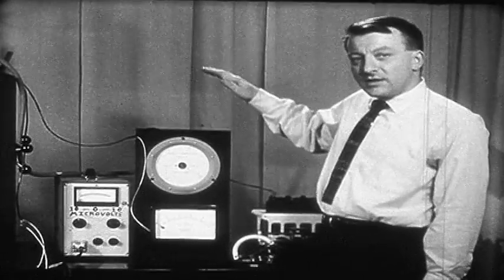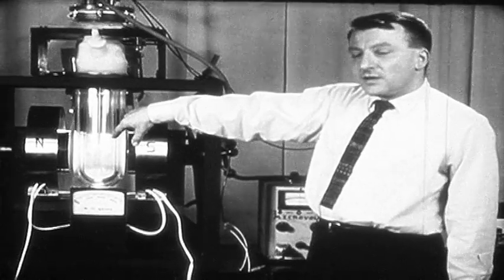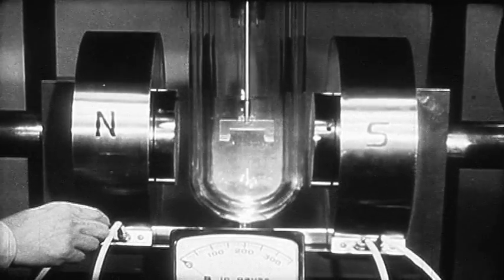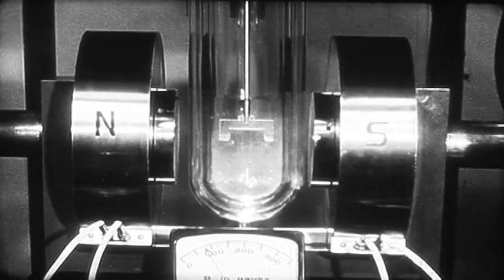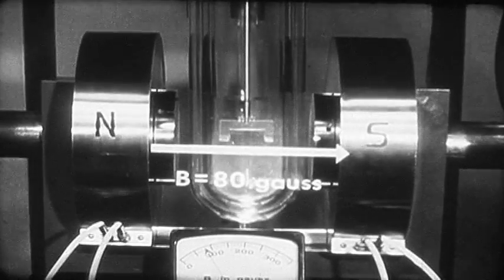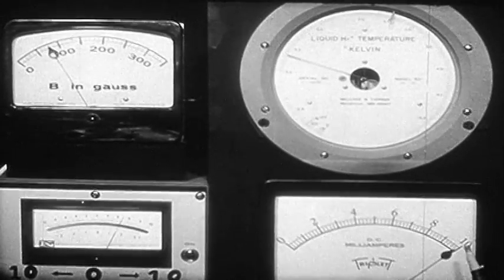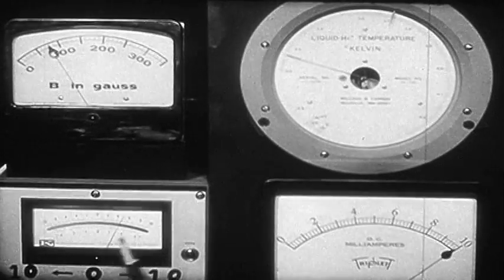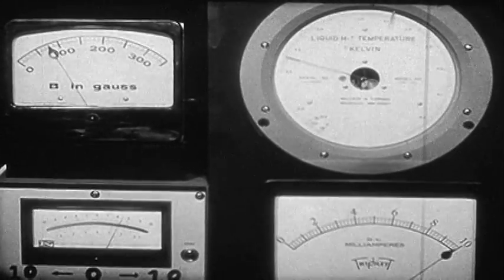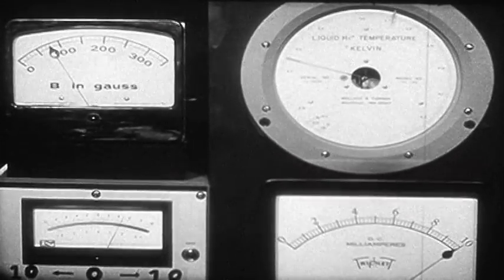To begin with, we again measure the transition temperature of tin using the short sample of tin wire, but this time we've put it parallel to the magnetic field of this electromagnet. For the fields at which we shall be using the magnet, its flux is proportional to the coil current. There is an ammeter in series with the coil, already calibrated in terms of the flux density prevailing in the central region between the pole pieces. The field at the wire is 80 Gauss. The same current which we used in the previous experiment is again flowing through the wire, and it registers the same IR drop on the microvolt meter. Clearly, the tin sample is in the normal state. But notice that its temperature is already much lower than 3.71 degrees Kelvin — marked off in the previous experiment as our value for the transition temperature of tin in the absence of an external magnetic field.